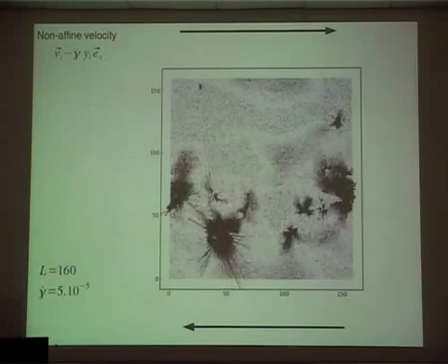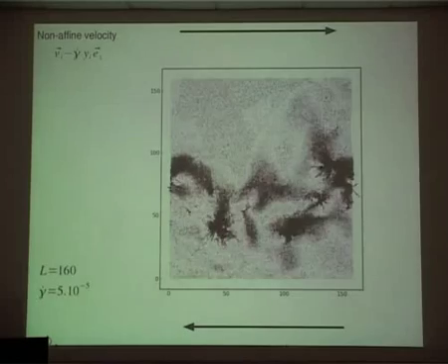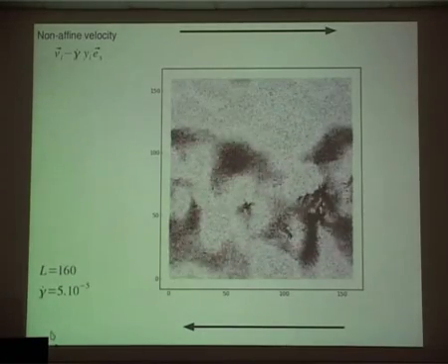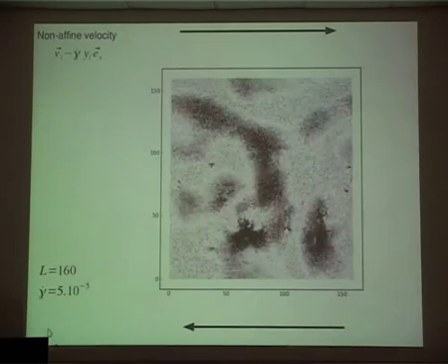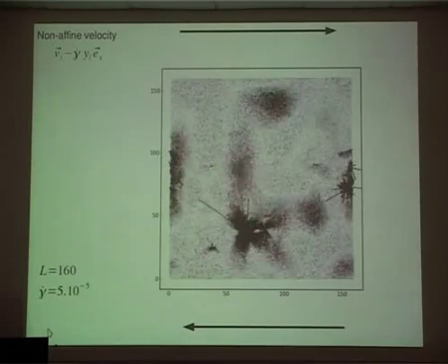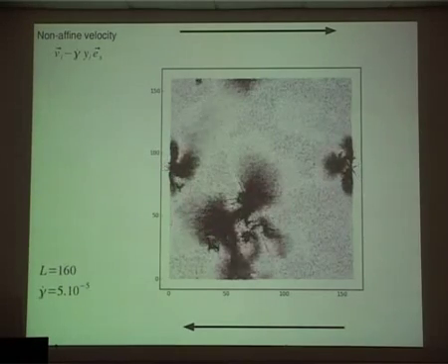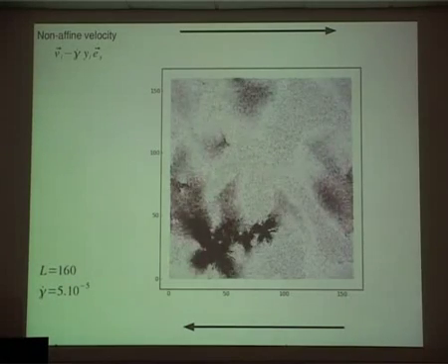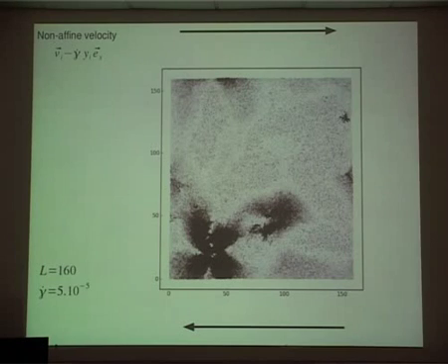The problem is that people have tried to relate this shear transformation to high stresses. It doesn't work. People have tried to relate that to low densities. It doesn't work. In fact, a shear transformation is a property of the local modulus. It's a soft region. It's more than a property of the modulus. It's a region which is soft and softening. So it's a property of the higher derivative. It's something very complicated to measure. And so it's not something that you can relate directly to a very simple structural property.